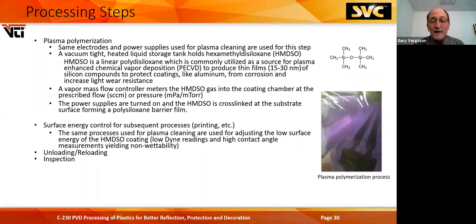Power supplies are turned on. Again, these are pretty high voltage, high frequency power supplies, and the HMDSO is cross-linked and forms a nice barrier layer on the coating, on the substrate, excuse me. Picture over here on the right, here are two of the electrodes. These are lights that are reflected on the window, not part of the process. And this is the chemical formulation here.